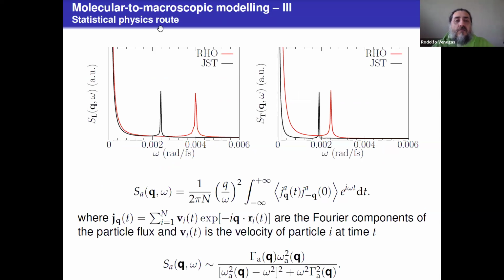So the first route is we get this spectrum, and this is what we fit with this expression. This is the way we calculate the dynamic structure factor from the molecular data. So J depends on the velocities that we can calculate from molecular dynamics. On the other hand, we consider the dynamic structure factor taking this form, which is essentially a mass-spring-damper system. So we calculate this from molecular dynamics simulations, and we fit this data using this model to get omega A, which are the eigenfrequencies, and from the eigenfrequencies we get the mechanical properties.